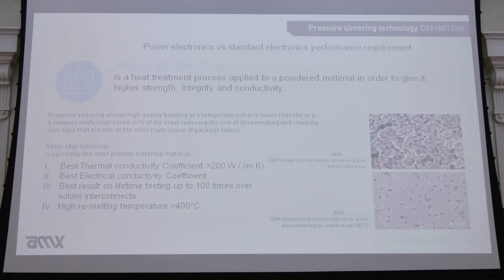Okay, what is pressure sintering? Pressure sintering is basically a heat treatment that consists in applying, obviously, temperature and pressure at the same time to a powder component. It can be silver, typically, or it can also be copper. Which are the benefits? The benefit is that we can have a reliable joint just adding 200-250 degrees Celsius in the process, but the melting point will be much higher. Roughly, we are in front of a piece of metal that will melt around 900 degrees Celsius. So you can really boost the performance of the circuit without any risk to the bonding.